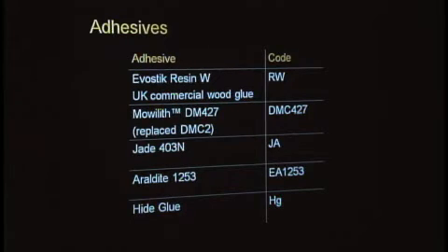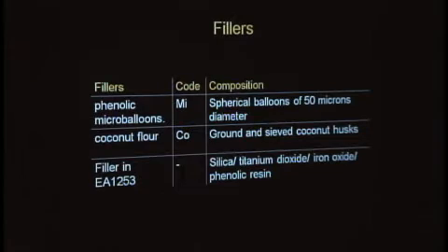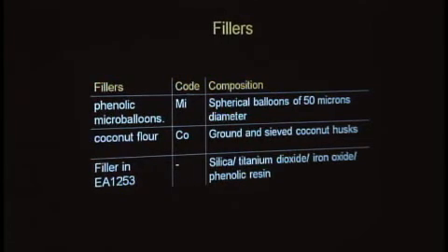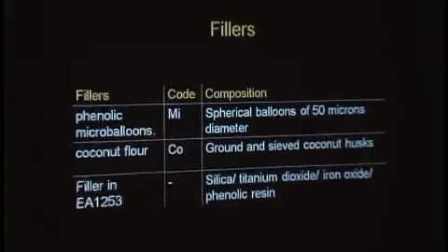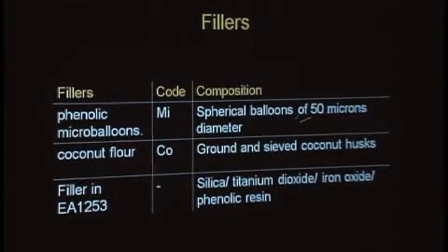It proves that it isn't, but it was nice to have at least something that was supposedly stable. Araldite, which George introduced us to, and we started to use it, being more used in the UK now, and hide glue as a contaminant as well as a filler. And the fillers that we concentrated on, again just looking at the relative properties, were these particular fillers. So the microballoons, these are spherical balloons of 50 microns diameter, and the coconut flour, which is basically ground and sieved coconut husks. And the filler that's already in the EA1253 is silica, titanium dioxide, iron oxide, and a phenolic resin.